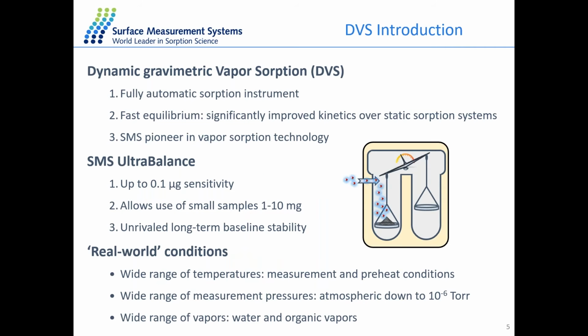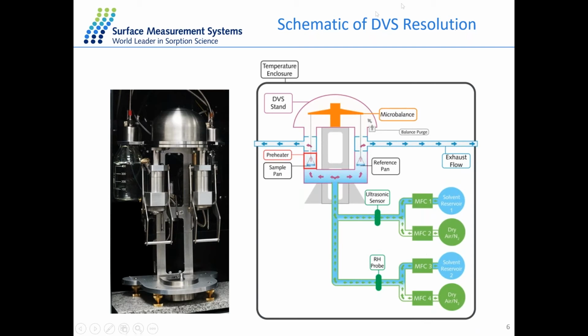DVS is short for Dynamic Vapour Sorption, which is basically a gravimetric method to measure the mass change of the sample at different concentrations of moisture and organic vapor. It has an ultra balance in the system with very high sensitivity, so we just need a very small amount of sample for the analysis, usually less than 10 milligrams. Compared to the static method, DVS has a continuous flow of the probe molecule to the sample, so we can achieve a much faster equilibrium. We can perform the experiment both at ambient temperature and pressure, and we also have a system to perform vacuum conditions during the experiment for some porous materials. Here I have an example of one of our systems, the DVS Resolution, which can perform the sorption of both water and organic vapor.